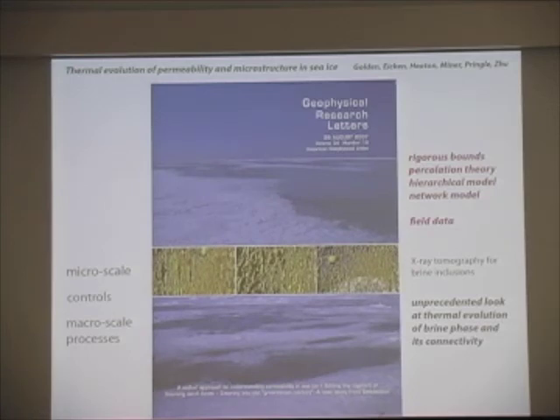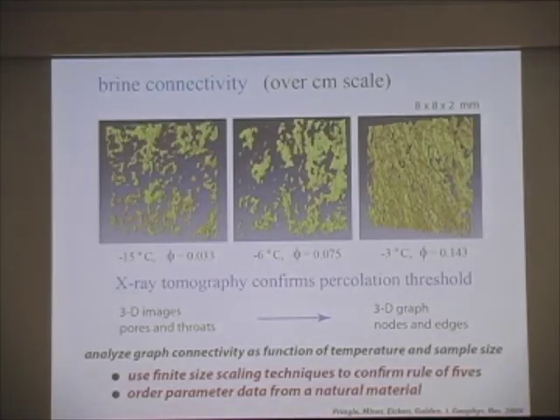Okay, so the next step though, after we established this threshold, was to figure out how the permeability changes with temperature or brine volume fraction. So this is the cover of Geophysical Research Letters. And again, I kind of consider this like homogenization in action. How does the small scale stuff, this is some of our X-ray tomography of the brine inclusions, control these larger scale processes such as the evolution of these melt ponds? Here you can see some of this evolution of the conductivity of the brine phase. And again, I conjectured this rule of fives, and the reasons for it, back in 1998, but it took at least another 10 years or so to develop this X-ray tomography method, so we could really, quote, prove my rule of fives.